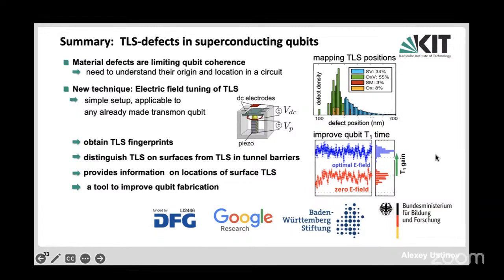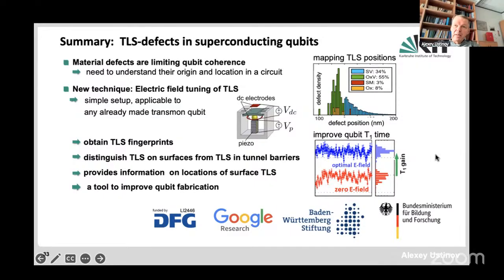So how much do you think the surface roughness of the superconductors matters? We don't know this well enough. So we know that surface roughness matters for the formation of the aluminum oxide. However, aluminum has a property, even in granular form when it grows, it has very good wetting to the oxide layer which forms. So even a granular bumpy layer of aluminum will form a higher quality tunnel barrier. The microscopics of that and surface chemistry of that is not fully understood to my knowledge. So there have been a lot of attempts to study aluminum oxide barriers, but at least to my knowledge, there is no clear understanding of what is happening there, how to get things better.